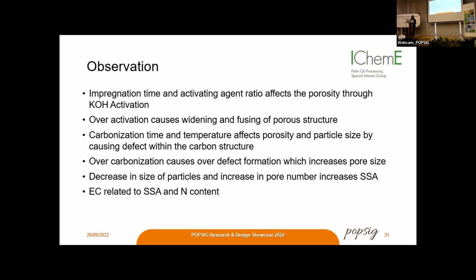So the main observations from this study are the impregnation time and activating agent ratio affect the porosity through KOH activation. Overactivation would cause widening and fusing of porous structure, which is not good, which also decreases the specific surface area. Carbonization time and temperature affect the porosity and particle size by causing defects within the carbon structure. Overcarbonization causes defect formation, which increases the pore size, and the decrease in size of the particle, as well as the increase in pores number, mainly hierarchical pores, increases the specific surface area. And lastly, the electrical conductivity is related to the specific surface area and nitrogen content.